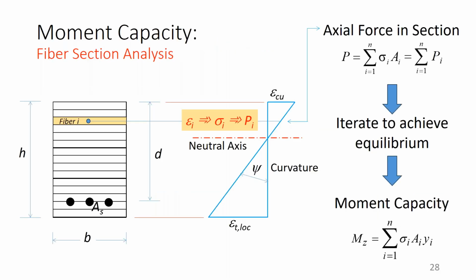And then we plug this into a fiber section analysis, and a fiber section analysis assumes that plane sections remain plane after bending. You slice the section up into slices, and then because you know the distribution of strains, for example, fiber I on the left there, if you go all the way to the right, you can get its strain for a particular level of curvature, and that means that you can go into the figures that I showed in the previous slide, get a stress. If you know the stress, you know the force.